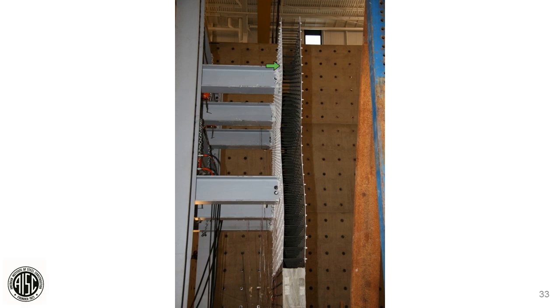But one of the things we're looking at on future projects is to space those cross ties out and potentially be pumping more, depending on the size of the core. Maybe we're going to pump two heights at a time, two lifts at a time. That could start to control how much bowing you might get during concrete placement. But again, we would limit it to a pretty small number, maybe a 1/16 of an inch or some sort of b over t ratio. But again, in Rainier Square's case, there was no observed distortion of any of the panels.